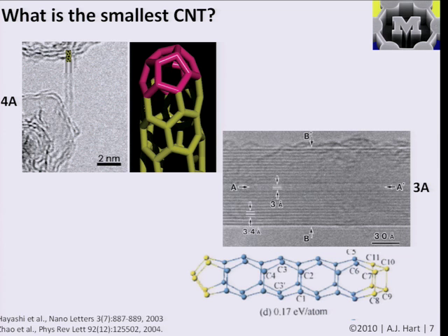Produced, and are they stable in long aspect? So they're going to be very easily degraded by air if you have defects in them. I don't know specifically how long they will last, but not only will they be easily degraded in ambient if they're this small, they'll also be easily degraded in the growth atmosphere, which is often more volatile because it contains some hydrogen, which can easily eat away at carbon that's not in the best state.